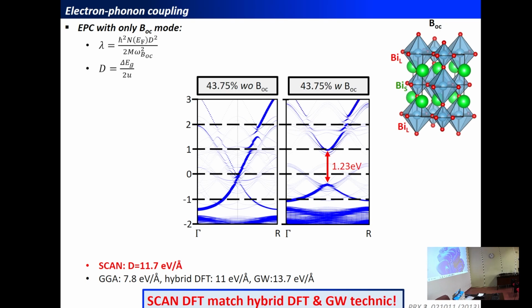To that end, we take the ground state, for instance, at 43% without the breathing distortion because it's not appearing in this situation. But then we add some displacement associated with this phonon in the band structure. And then we compute the band gap opening associated with this vibration. If we do that, we end up with a reduced electron-phonon coupling matrix element around 12 electron volt per angstrom, which is an improvement over the LDA or GGA calculations that give between 5 and 8 electron volt per angstrom. But also it's in very good agreement with the best calculation we can do with hybrid DFT, which gives 11, or the Green's function calculations that give an upper value, around 13 to 14 electron volt per angstrom. And so this SCAN functional, the functional we are using there, is giving reduced electron-phonon coupling matrix elements which are reminiscent of previous literature using more elaborate techniques.